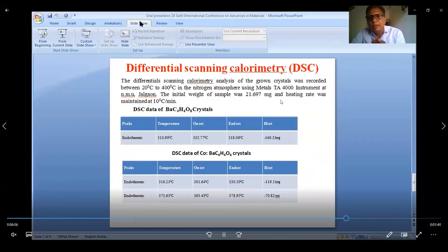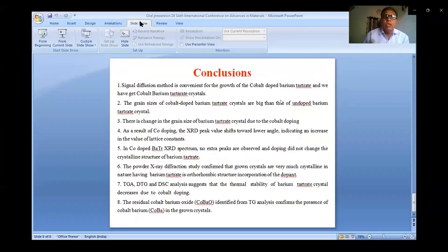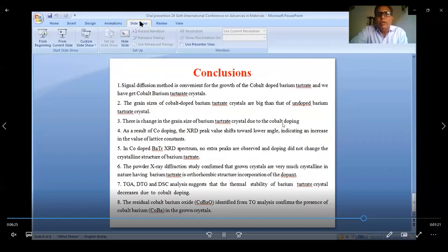So the conclusion is that the single diffusion method is convenient for the growth of cobalt doped barium tartarate crystals. The grain size of cobalt doped barium tartarate crystals is bigger than that of undoped barium tartarate crystals. Third, there is a change in the grain size of barium tartarate crystals due to cobalt doping. As a result of the cobalt doping, XRD values shift toward lower angle, indicating increasing.